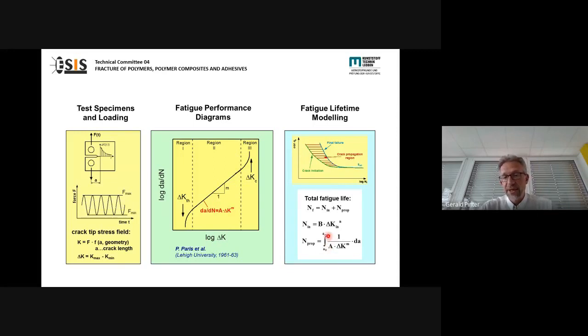So you can integrate the Paris plot from an initial defect to the thickness of a component or thickness of a specimen, and get the lifetime for the propagation of the crack. But you also have to consider, of course, the cycle number until a crack initiates. So you need a material law for that. And by the summation of these two parts, you get a failure time for fracture mechanics fatigue applications.